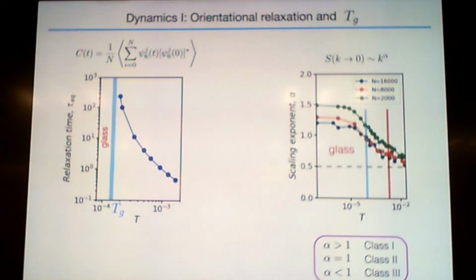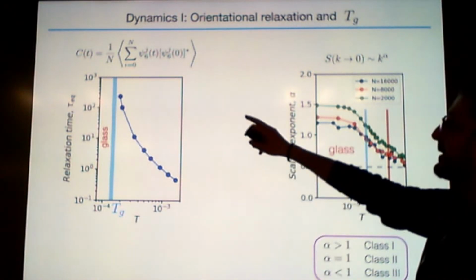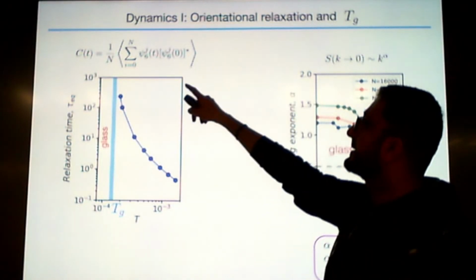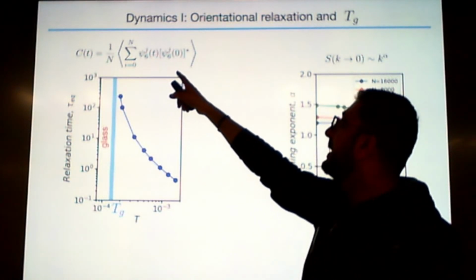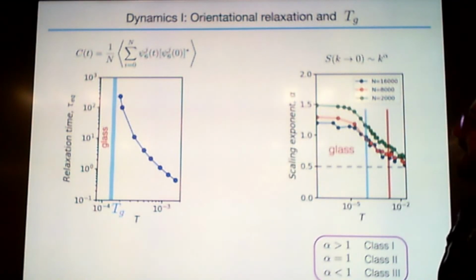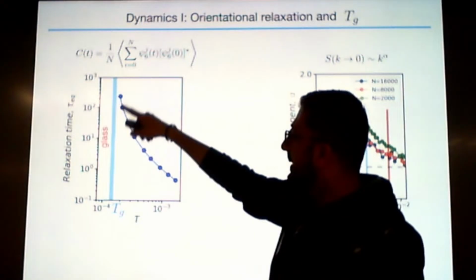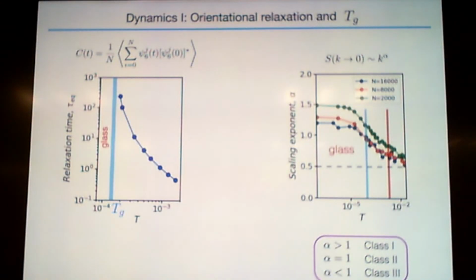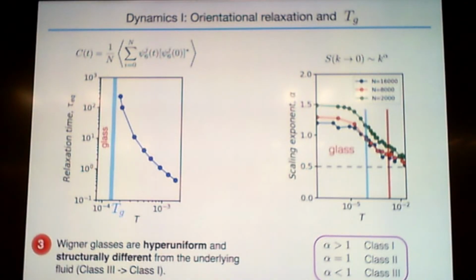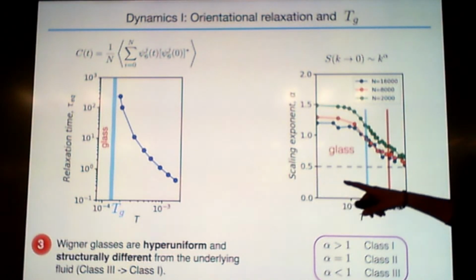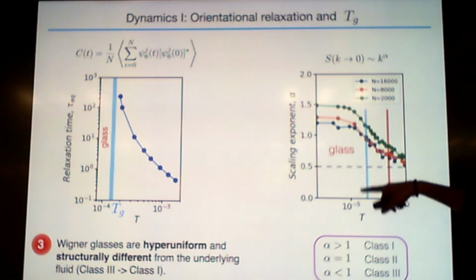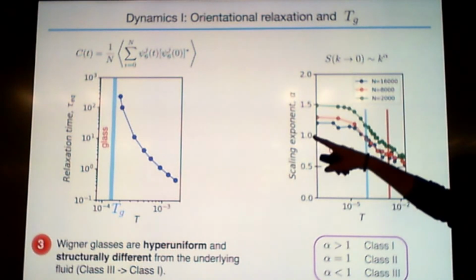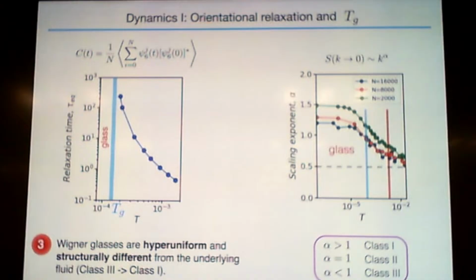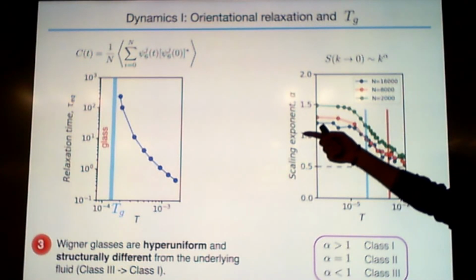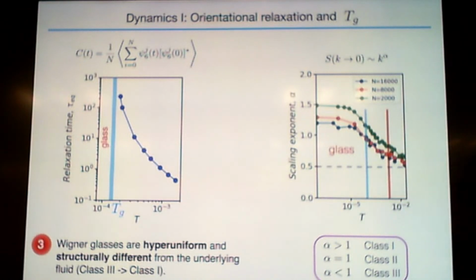All right, so what we do here is we measure the correlations in the orientational relaxation, psi six, as a function of time. And we see that these correlations diverge at this temperature, which we call Tg. That is indicative that once you reach this Tg, you go from one class to another class of hyperuniformity. So you're crossing this one line. This also holds for a different S, by the way, not only for this S.